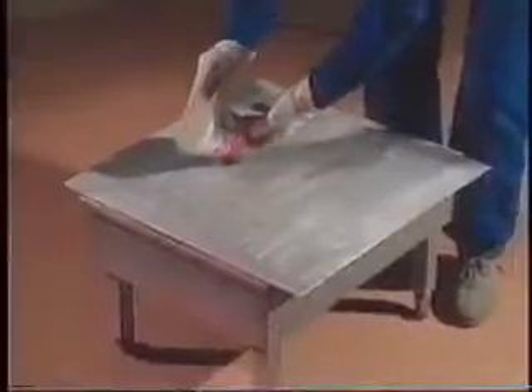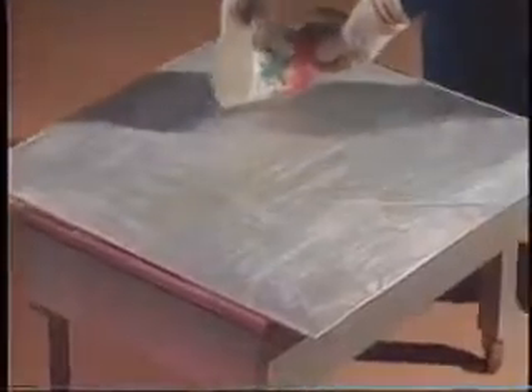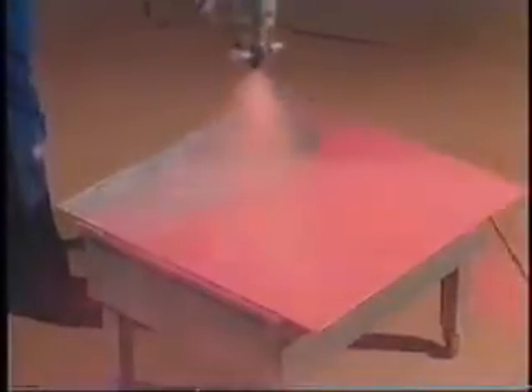Envirolastic, unlike polyurethanes, can also cure on damp surfaces. Envirolastic is not moisture sensitive and will not foam or pinhole around moisture. This is just water, and you know what happens when you get polyurethanes around even high humidity. The Envirolastic, however, still cures completely.